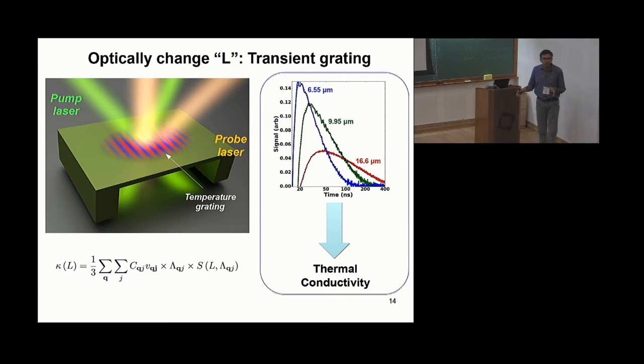So this is the recipe: you do experiments of thermal conductivity at different length scales, in this case grating period, and then invert this equation to get phonon mean-free paths or phonon-specific information. This is the recipe that I have used.